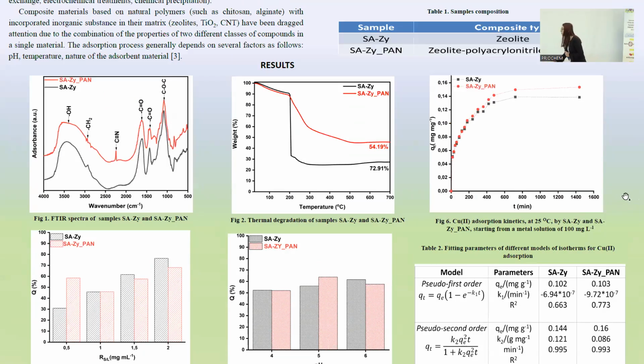The next test was the selectivity for nickel and copper, and we can see a better affinity for copper compared with nickel. And the last test, we see the kinetic study of the sample. I used two different kinetic models, pseudo first order and pseudo second order. We can see here we have good results for the pseudo second order. That means we have chemical adsorption of the materials.